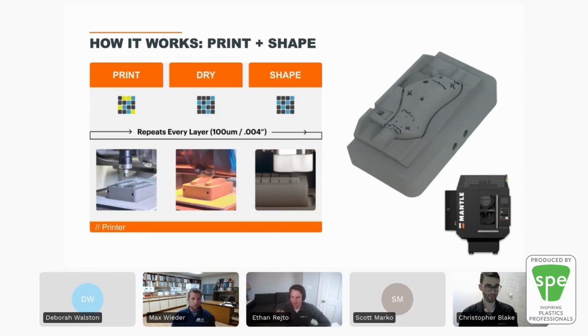So if you can see in my little illustration up top, those yellow bricks are gone because now we've removed the solvent out of the material, firmed it up, and then we machine it. Every single layer, this is happening over and over again to build up the part. Since the material is very soft in this stage, it's just a dried paste, we can machine really quickly.